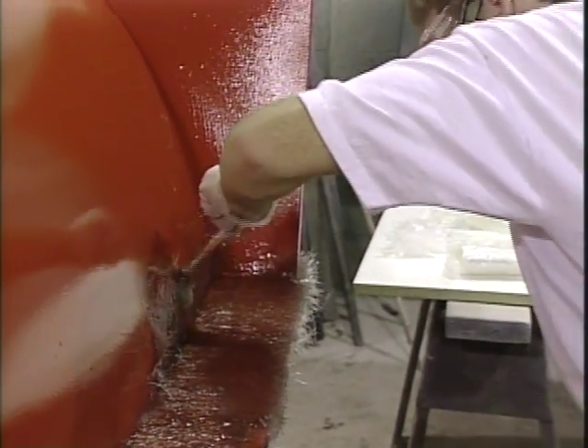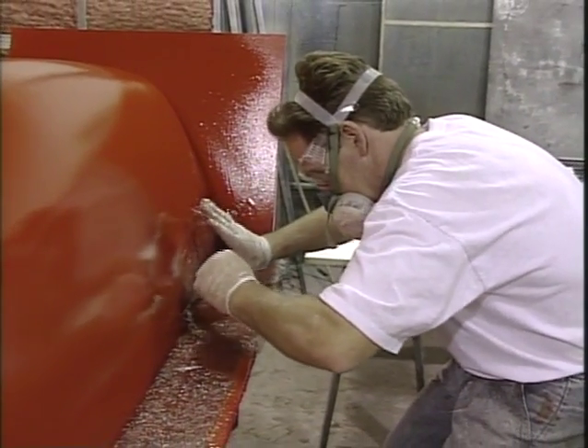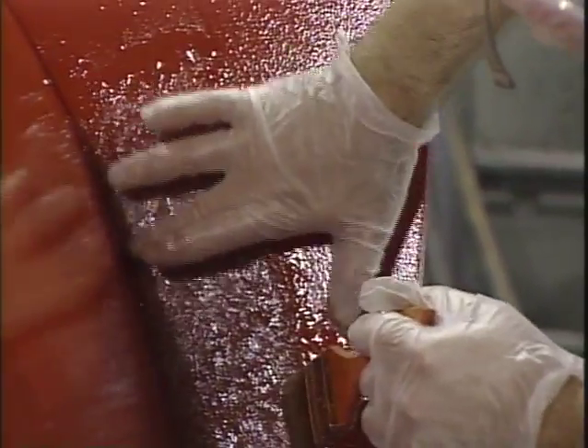We also cut a number of strips of mat about 8 inches wide. These I tore in half, which left 2 strips with a single cut edge and 1 frayed edge. I placed the frayed edge strips onto the plug surface by butting the cut edge into the corner against the flange. The frayed edge drapes evenly onto the plug surface where the other layers may be applied over it without trapping air pockets. This butt joint at the corners effectively eliminates air bubbles.